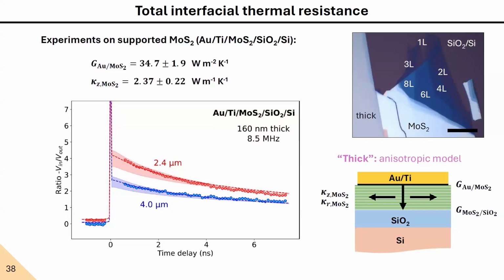But both of these signals are influenced by the optical properties of the film, the reflectivity and so on, and therefore our thought that we could have coherent phonon effects. But the ratio of the two signals is not affected anymore by the optical properties, because they have the same dependencies and you divide one by the other. So you remove this contribution, and therefore your signal mainly decays as a result of heat transport properties.